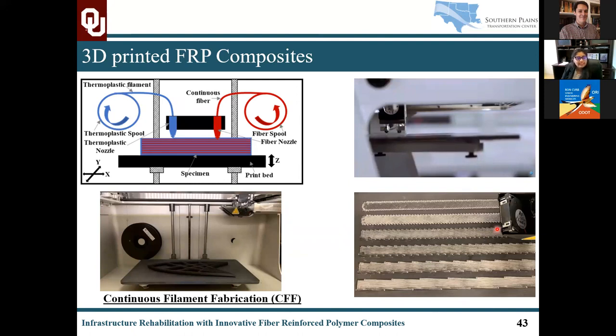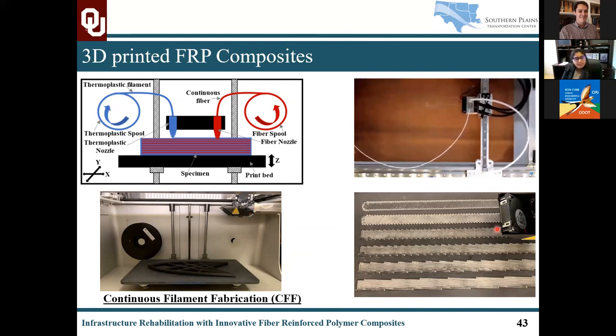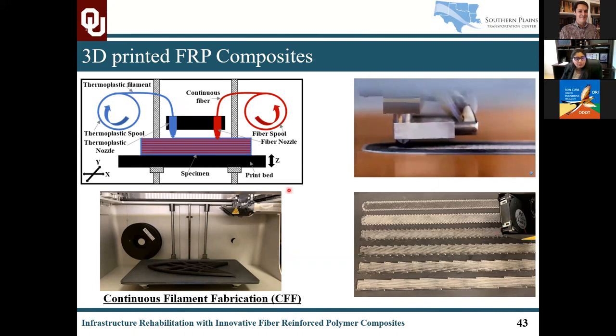What 3D printing offers is very interesting, because advanced 3D printing technologies currently have the capability of not just printing thermoplastic spools, but also printing with fiber spools. This can be simultaneous, and this can also be one when one is running, one does not run. And this is basically resulting in a selective reinforcement capability. So this advanced 3D printing technology is beneficial in producing FRP composites with engineered stacking sequence. Individual layers, for example, can be produced with different fiber orientations. So as the component is being built in these different layers, each layer can take the form of a different fiber orientation, which in turn affects the mechanical behavior of the FRP composite systems.